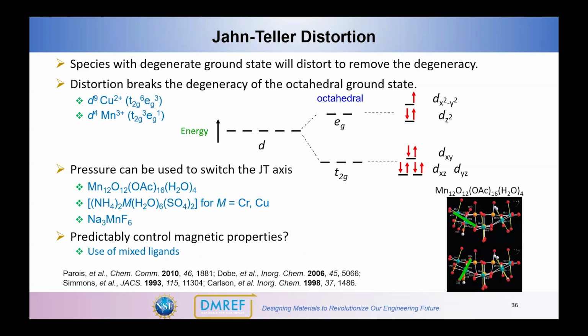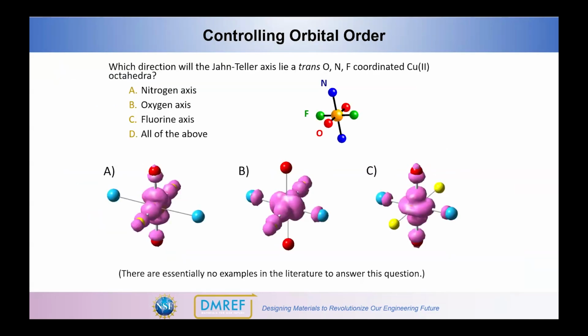And so I'm not going to really have time to talk about this, but we were very interested in looking at the effect of the Jahn-Teller distortion in copper-based coordination polymers and how we can control the Jahn-Teller axis and the magnetic orbitals. And so this is a question that I would throw up: in what direction would the Jahn-Teller axis lie if you have a trans octahedra that has oxygen, nitrogen, and fluoride around it? And there was essentially no answer to that question in the literature, but really the answer is kind of all of the above.